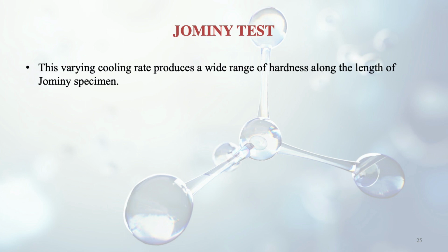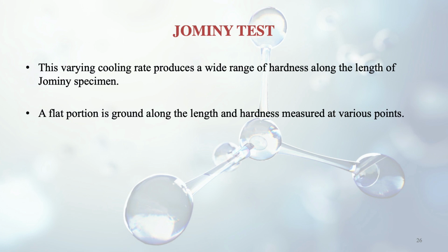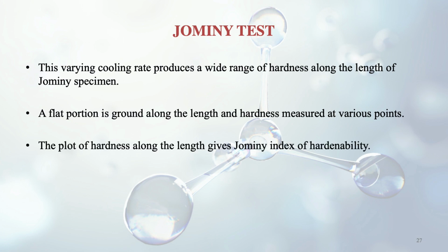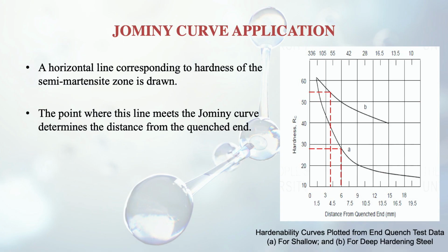So this varying cooling rate produces a wide range of hardness along the length of the Jominy specimen. So we know that with cooling rate the hardness varies. If the cooling rate is different at one end and different at the other end, obviously the hardness attained in that specimen will also be different at different portions. A flat portion is ground along the length and hardness measured at various points, and the plot of hardness along the length gives us the Jominy index of hardenability. So you see in this figure, the distance from the quenched end in millimeter is on the x-axis, and hardness is on the y-axis. This is the Rockwell hardness RC, as we have studied earlier.